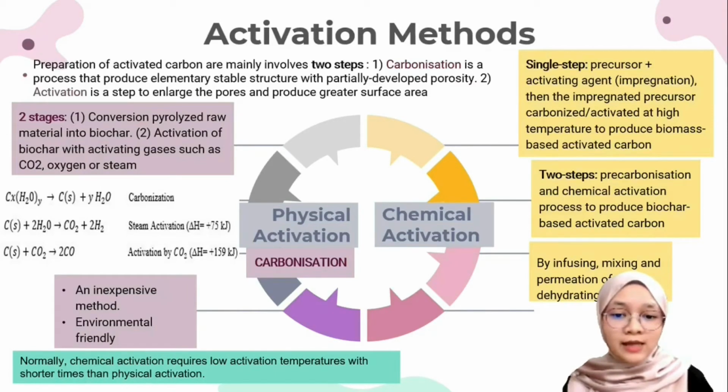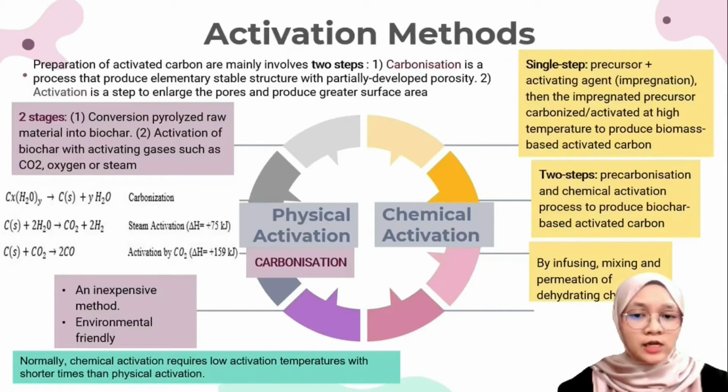These activating agents deeply penetrate into the internal surface of activated carbon, contributing to development of smaller pores, thereby increasing surface area. Normally, chemical activation requires low activation temperature with shorter time than physical activation. Therefore, it results in higher yield of activated carbon than physical activation.